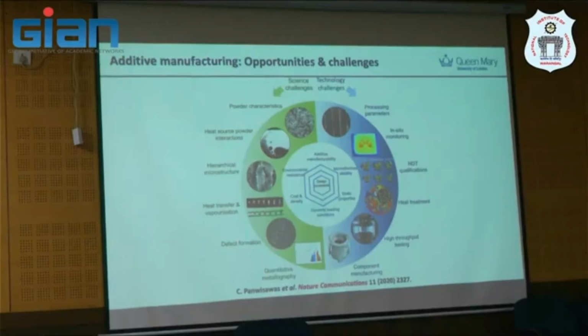So heat transfer and composition change is another challenge that I'm trying to tackle. For example, if you have composition material A, but finally you're printing material B at the end, because the nickel actually is lost by a few atomic percent, which totally changes the phase transformation that you want, let's say, in nickel titanium. There is a paper already published with the University of Birmingham saying that nickel can lose up to 2 atomic percent. That changes the martensitic transformation temperature in the body, 37 degrees, for example.